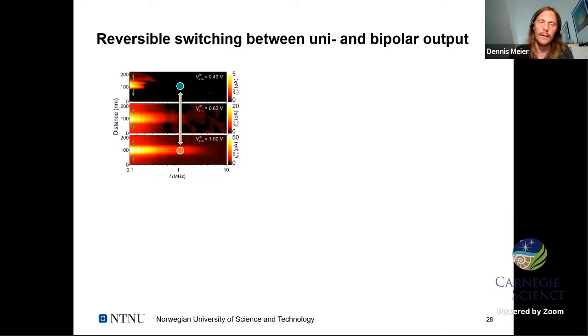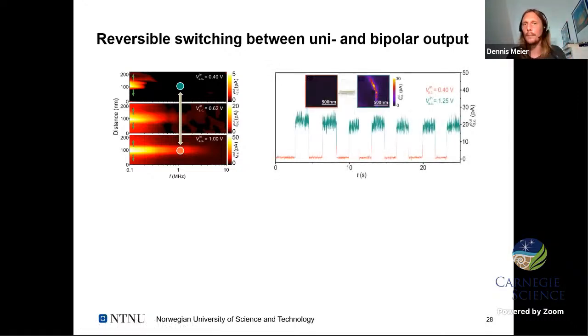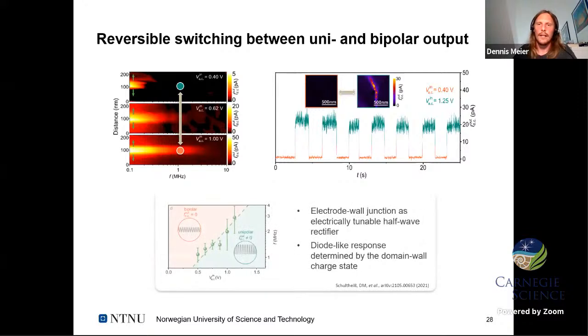So the walls here have a bipolar response, whereas at 1 volt, you see that we have a strong rectifying behavior. So I can now go to a certain frequency and switch forth and back and play the same game as I already did with the DC current at the head-to-head wall. But what I'm doing here now is I'm switching back and forth between uni and bipolar behavior by changing the voltage we apply to the domain walls. So the electrode wall junction can really be used to deterministically control the response we get from the walls.